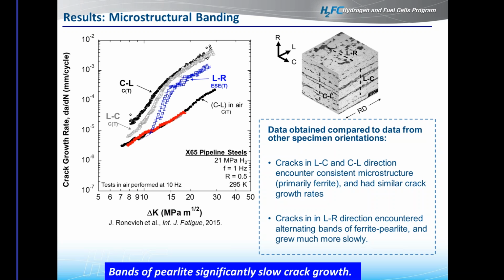So what we found was that the data in air, as I said, is consistent between the X65 and the X52 from the previous few slides. But we see that the CL orientation and the LC orientation showed a little bit of difference at the lower delta Ks, but really started to converge at the higher delta K region. The LR orientation was very interesting because it showed lower crack growth rates throughout the entire delta K range that we tested at. And this really highlights that microstructure does seem to have an influence on how these crack growth rates are occurring.